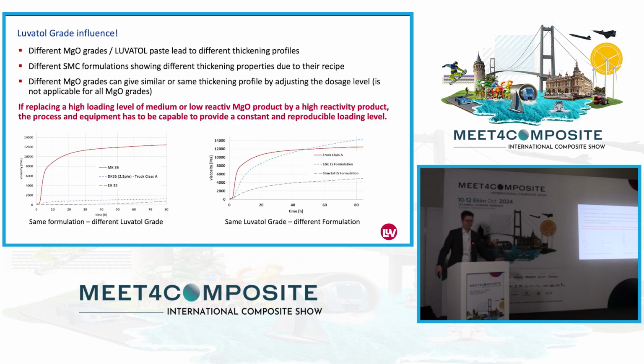First and easiest thing is the Luvatol type. Again, we have totally different grades, and not only magnesium oxide, hydroxide can also be used to thicken your SMC process. Here on the bottom, you see a chart with viscosity. We measure the complex viscosity with a rheometer against time, the thickening time. We always use the same resin. In our laboratory, we always use an AOC resin for testing, and we always use the same amount of magnesium oxide paste in it to compare.